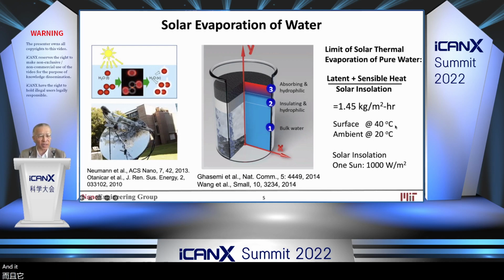And it turns out that there is a fundamental limit on that. We know how much energy is in the sunlight, and in standard terms it is about 1,000 watts per meter square. You convert that energy over 1 hour, see how much energy it has, and ask how much water it can evaporate. The value is about 1.4 or 1.5 kilograms per meter square per hour. So you can think of this as a fundamental limit, right? That's the maximum amount of water you can evaporate if you convert all the solar energy from the sun into heat.